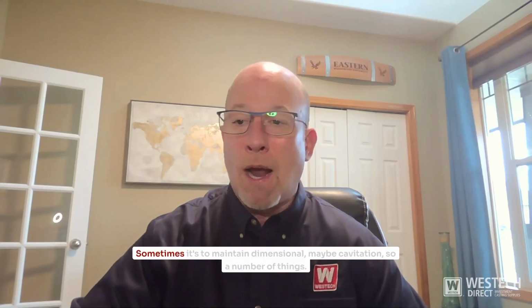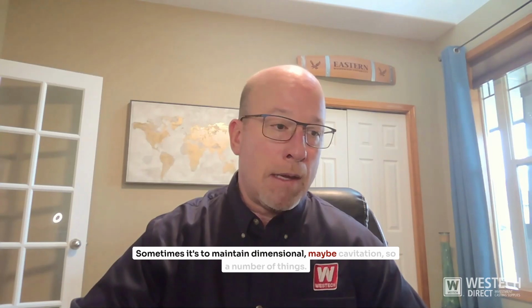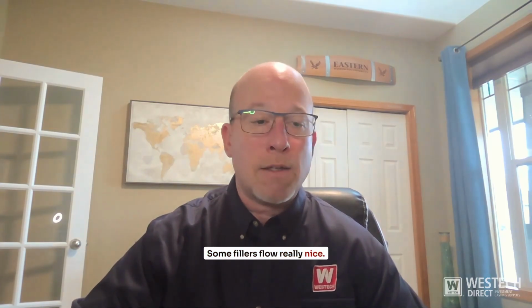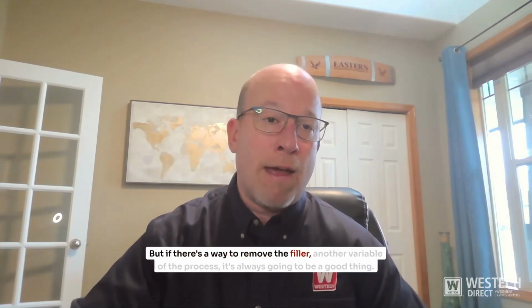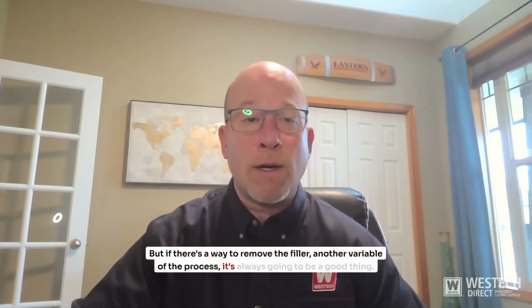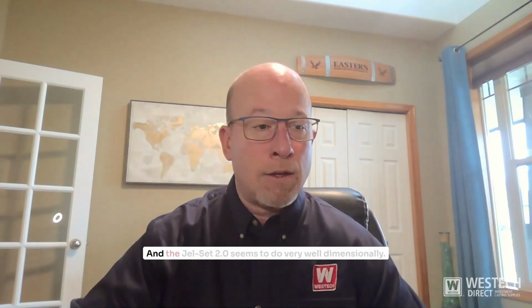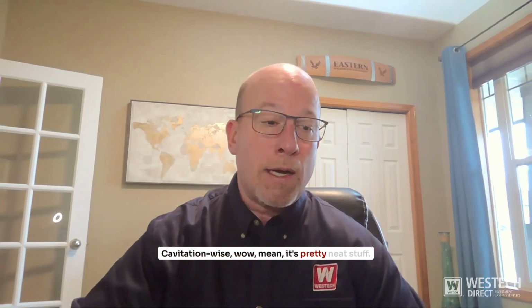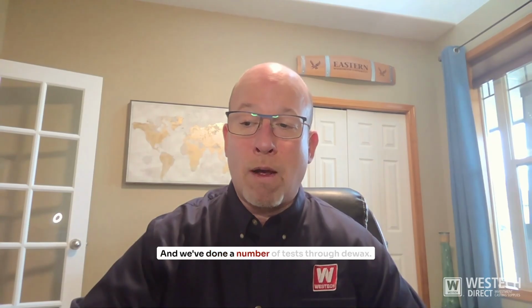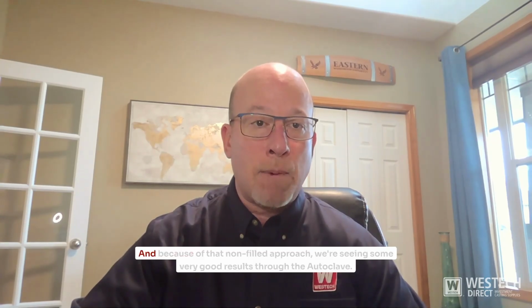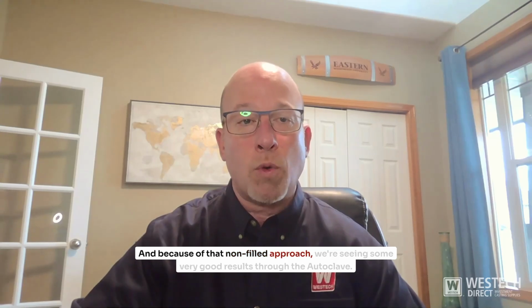Filler is very important. Sometimes it's to maintain dimensional stability, maybe cavitation, so a number of things. Some fillers flow really nice, but if there's a way to remove the filler, that's another variable of the process, and it's always going to be a good thing. And the Jel-Set 2.0 seems to do very well dimensionally, cavitation wise. Wow, it's pretty neat stuff. And we've done a number of tests through dewax, and because of that non-filled approach, we're seeing some very good results through the autoclave. Eduardo?